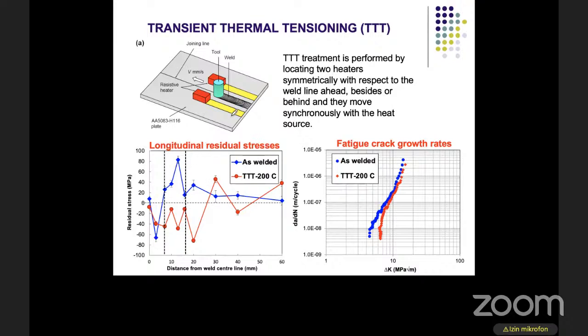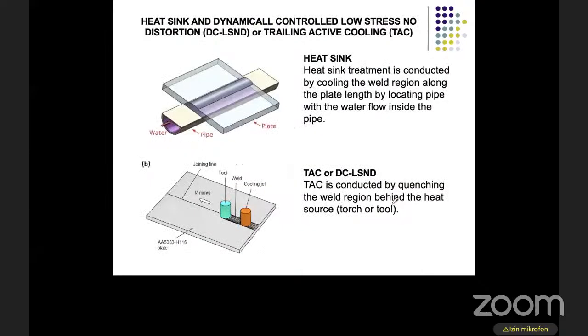It shows that the TTT treatment is proved to be a better method to reduce residual stress. And we can see also the fatigue crack rate. You can see that the TTT treatment effectively reduces fatigue crack growth rate. And then we also studied the heat sink by locating this cooling jet using liquid nitrogen. We quench here. The reason is to generate a thermal gradient. So in this case, it produced compressive tensioning. The principle is the same as static thermal tensioning. So in here, the residual stress can be reduced.